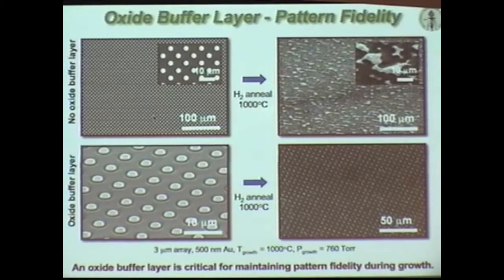We do that by either stamping or, in this case, photolithographically patterning little gold, nickel, or copper catalyst balls on a silicon wafer. And when we tried to grow structures with that, they should grow epitaxially underneath these metal catalyst particles that crack the chlorosilane and then precipitate the crystal of silicon. The gold rides on top, and it seeds this just like growing corn, kind of like nanobio corn. Except that we got nothing.